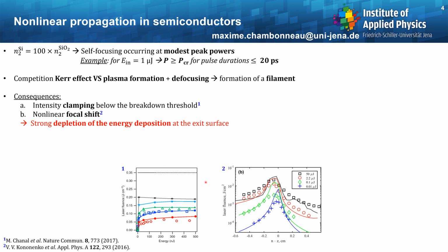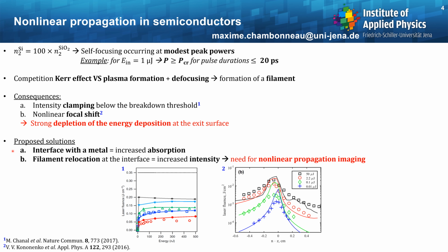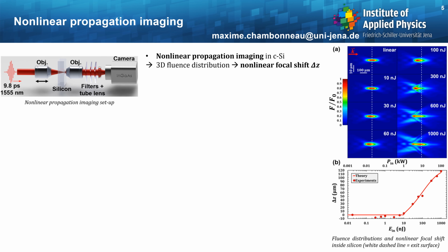So what solutions can we propose for achieving semiconductor metal laser welding? Well, first, we will of course use an interface with a metal, meaning that the absorption is increased, which is good. And second, we propose a filament relocation at the interface between the two materials, meaning that the intensity will be increased. But to do so, we need nonlinear propagation imaging. And this is exactly what we did.